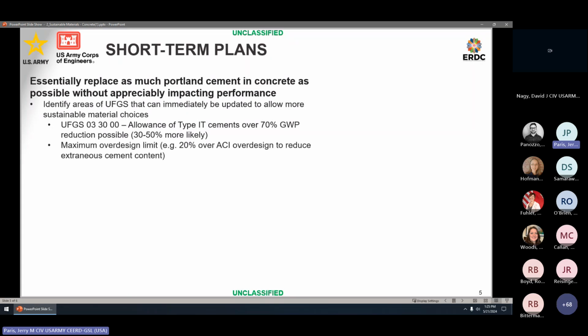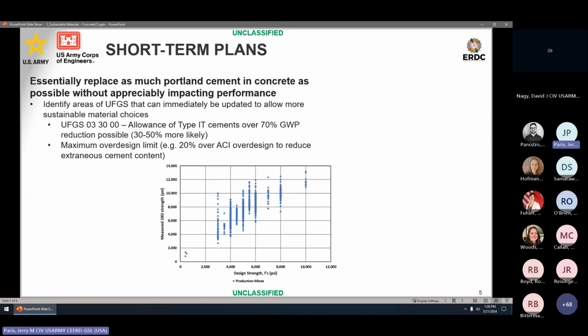We're also debating about including an over design limit. So for structural concrete, in order to guarantee that the vast majority of your concrete meets the minimum design strength, there's an over design. And so what we're thinking about doing is including a limit to how much over design is built into it. So as an example, this is a chart of over 850 production mixes from a ready mix facility. And on the x-axis, what we have is design concrete strength rather. And on the y-axis is the actual measured strength at 28 days. And in an ideal world, all of these points would line up on this line, right? Your strength that you design is exactly what you get.